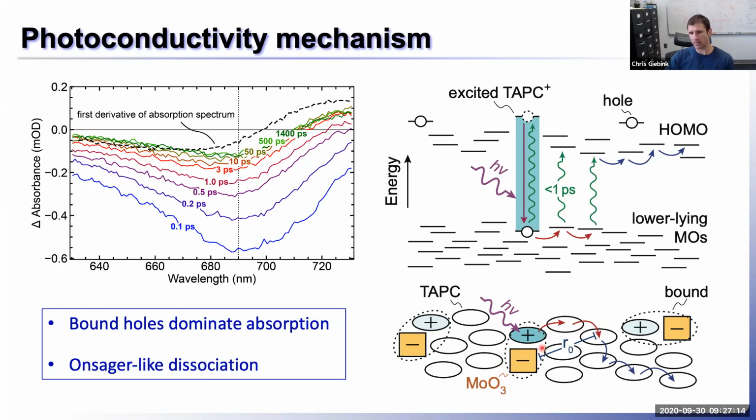And so we set up electroabsorption of nearby cations. And so we see this electroabsorption spectrum persist over much longer time scales, nanoseconds and even longer, until the charge carrier distribution returns to what it is in equilibrium. So this is the picture for photocurrent in a bare film.